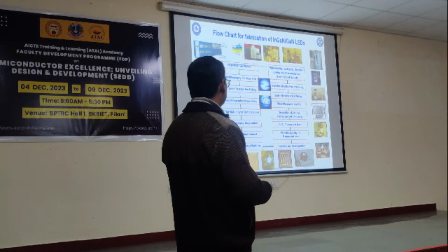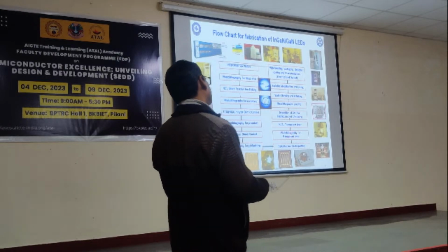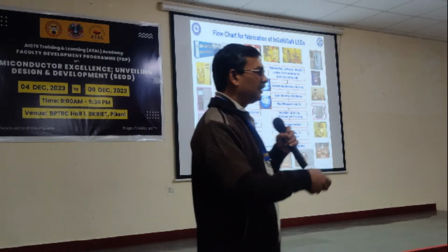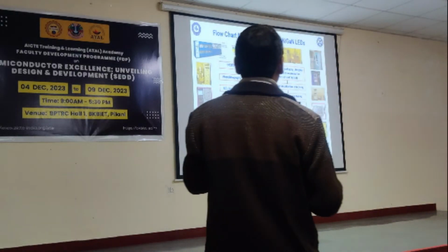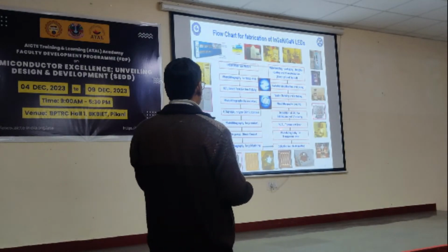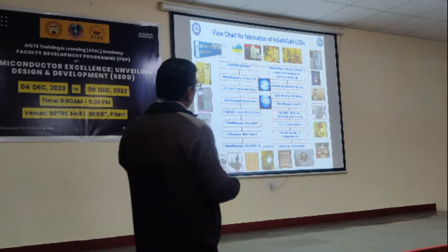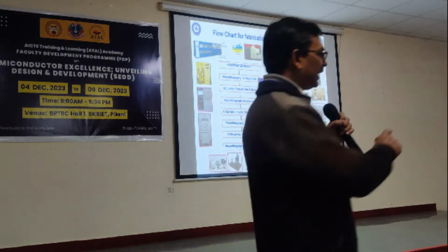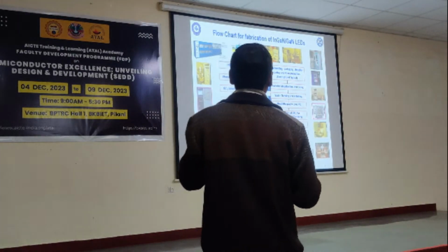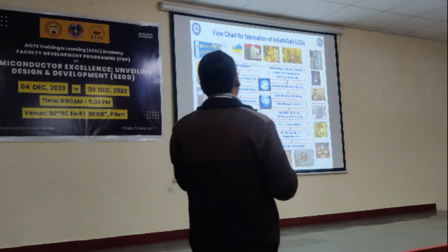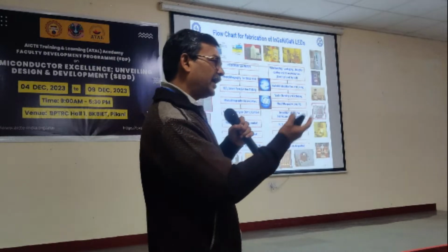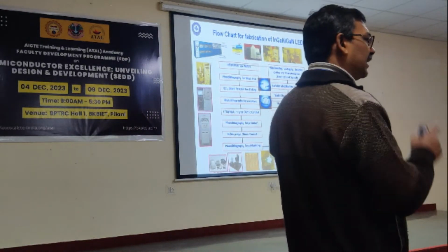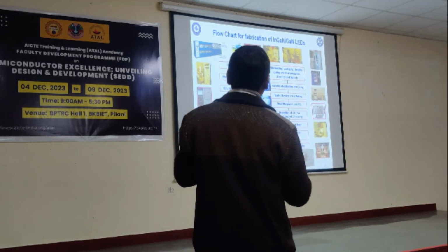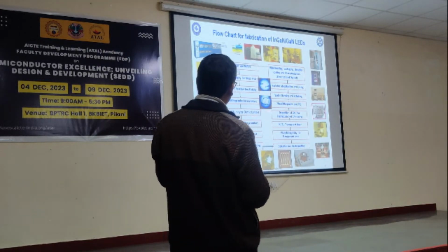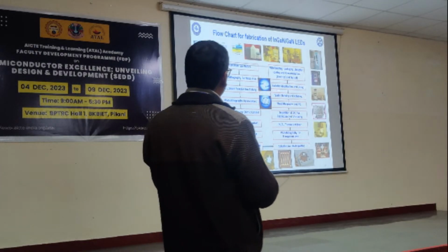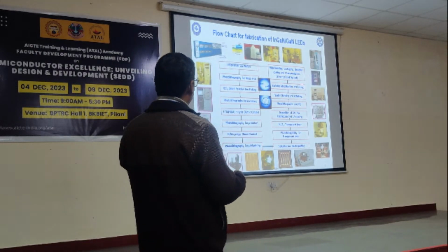This is electroplating. After electroplating, we go for another photolithography for the transparent conducting layer in the emission area. We deposit a very thin transparent layer of nickel gold. Then again we deposit a very thin layer of oxide, for isolation or anti-reflection coating. And again we go for photolithography, etching, then wafer thinning on the back side. Then we dice as per the device size. So we grow on a wafer, and after that we dice in terms of the device size. And then we go for bonding and packaging.